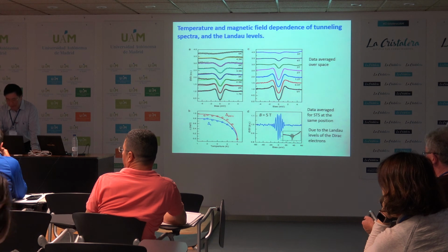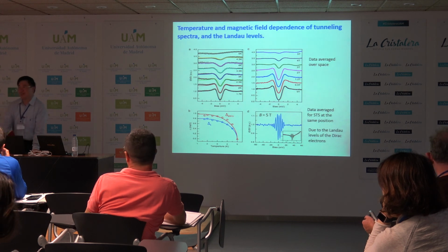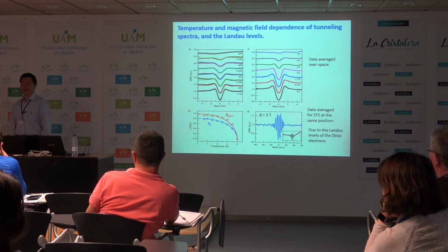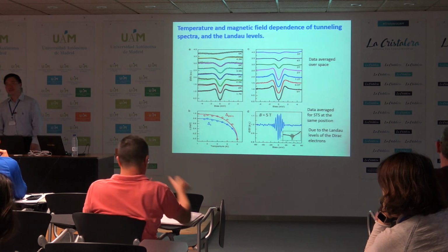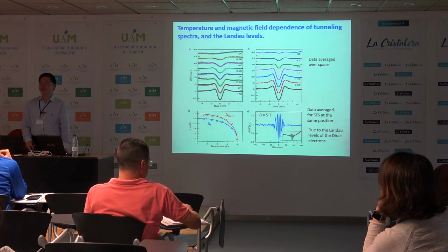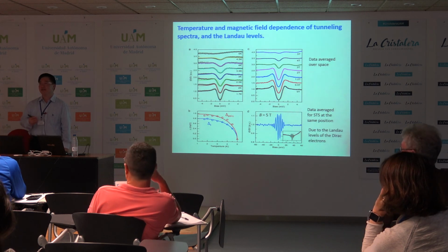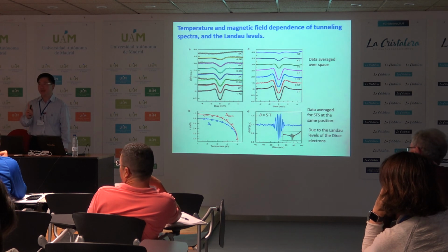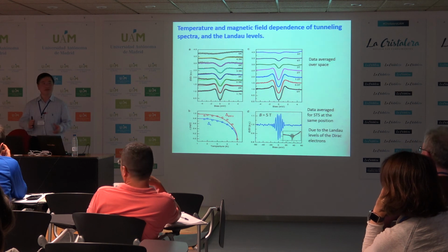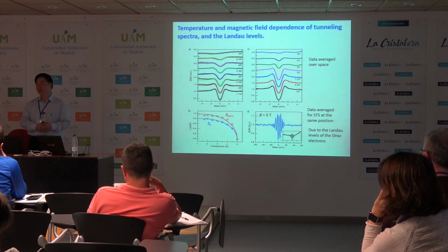As I said, as a scientist, what I saw, I can say. So that's my point. Last year, we measured 30 vortices, and as I said, maybe 40 to 50% show a peak, a giant peak, but not really sitting at zero. So that's our claim in the paper. Now this year we measure more and more, but still the percentage is not so high.